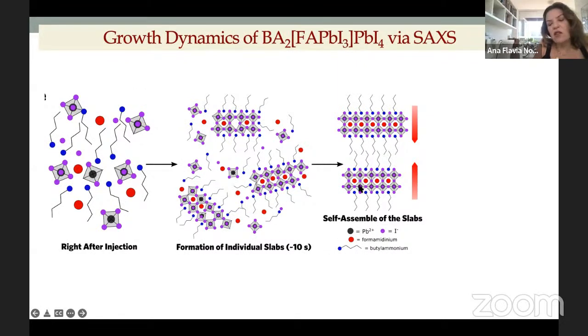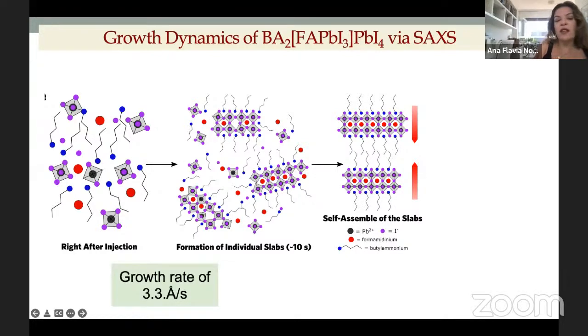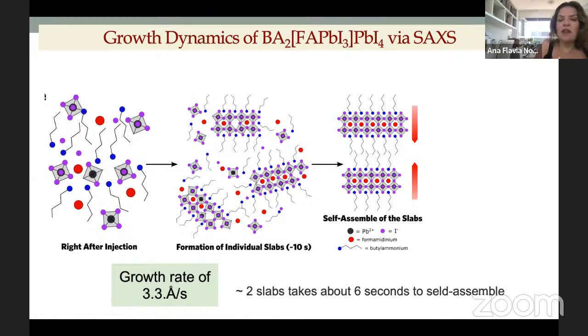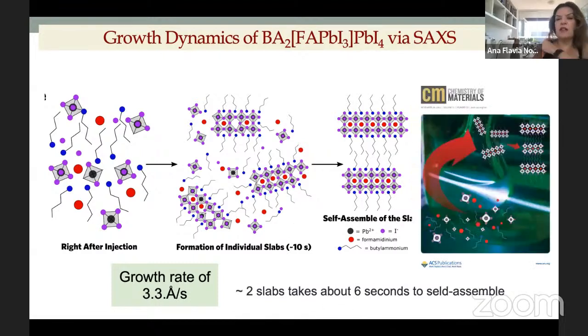So after 10 seconds, you see here the self-assembling of these slabs. As we are doing this in situ, we can calculate the growth rates. It was about 3.3 angstroms per second. What does it mean? It means that two slabs like that take about 6 seconds to self-assemble. This work was a front cover of Chemistry of Materials in 2019. I think it was the first time in the literature that we could see the formation of these 2D materials in solution.